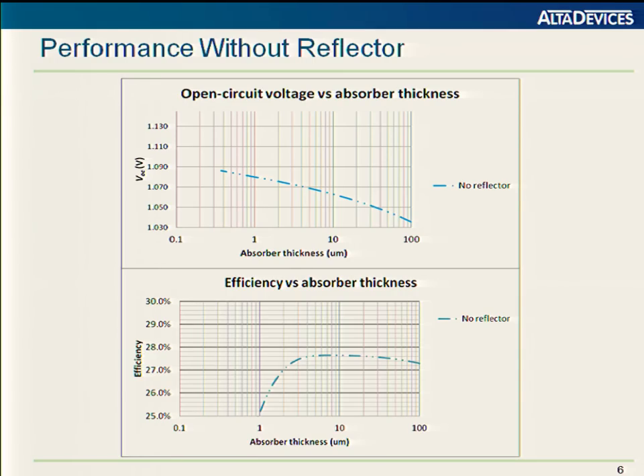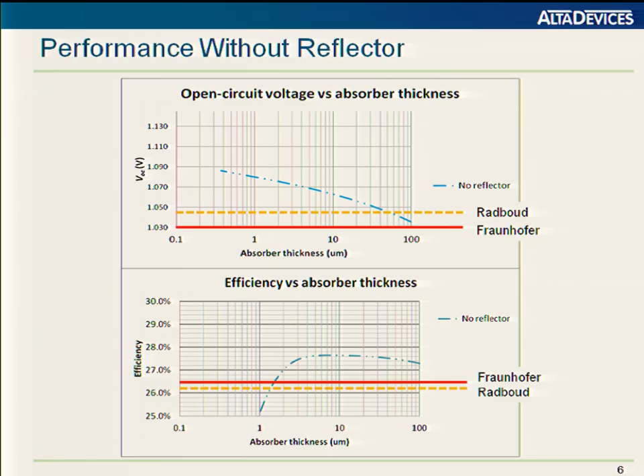So using the same model to look at VOC and efficiency in such a device with a thick crystal substrate and no reflector. Even theoretically, the VOCs are limited to less than 1.07, and the efficiencies around 27%. And in terms of practically achievable, using these same groups' data, real VOCs are below 1.05, and efficiencies in the mid 26% range, 26.4 from Fraunhofer.